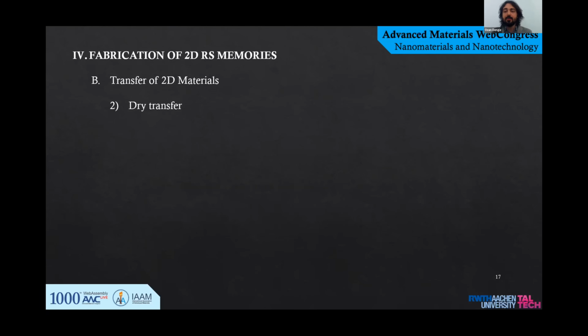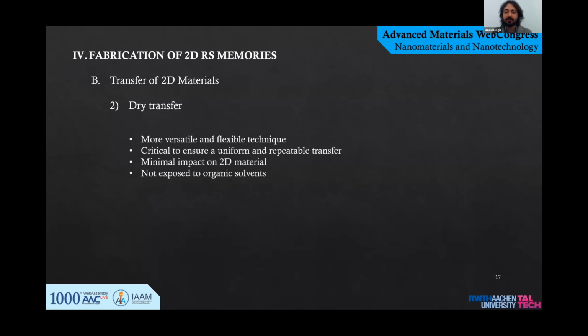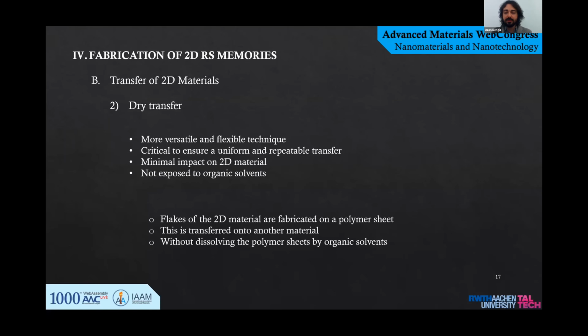Dry transfer is a more flexible technique to explore heterostructures, which is critical to ensure a uniform and repeatable transfer with minimal impact on the 2D material. It does not require them to be exposed to organic solvents. In dry transfer, flakes of the 2D material are fabricated on a polymer sheet. Then it is transferred onto another material, like exfoliated hBN on a silicon substrate, without dissolving the polymer sheets by organic solvents.